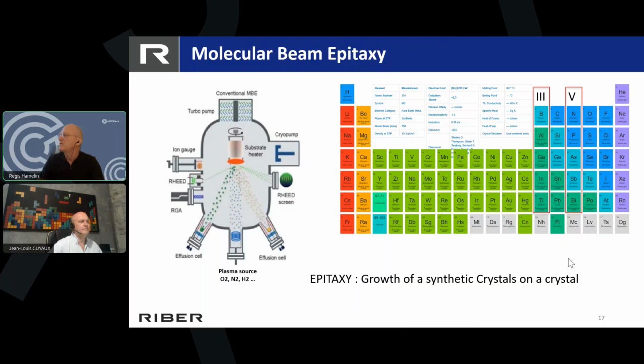And for BTO, this will be the next machine. BTO is a material you are able to grow epitaxially on silicon. However, for the growth of oxides on silicon, you have to have a seed layer, which is mainly based on strontium oxide on silicon. The strontium and the barium are evaporated under vacuum, while the titanium is evaporated through an e-gun. Oxygen is brought into the machine as a molecular source or an atomic source, using a plasma source.